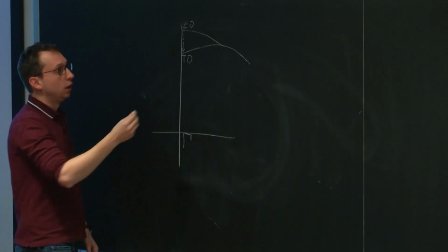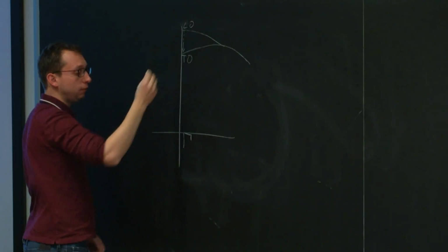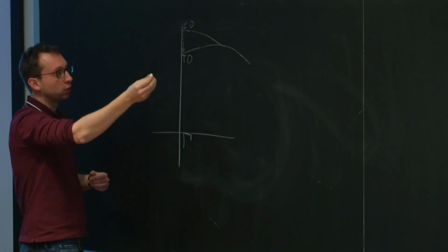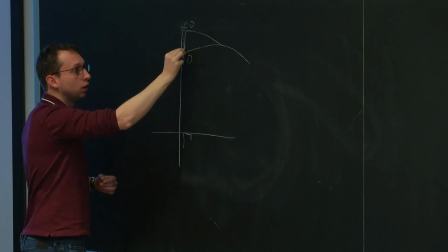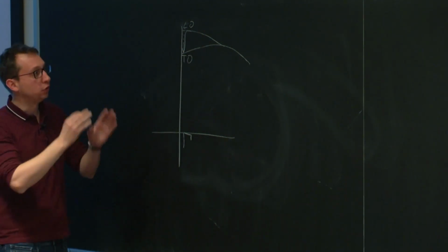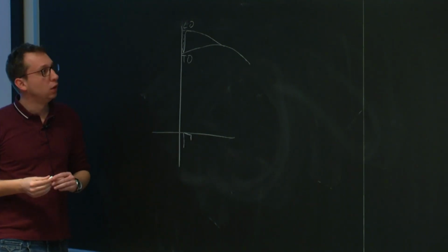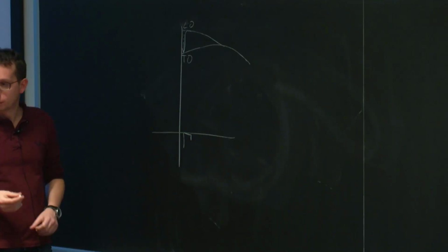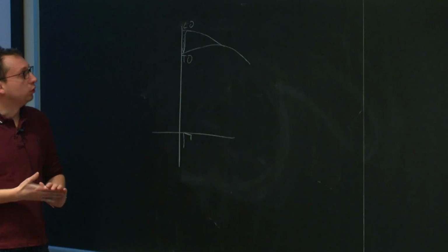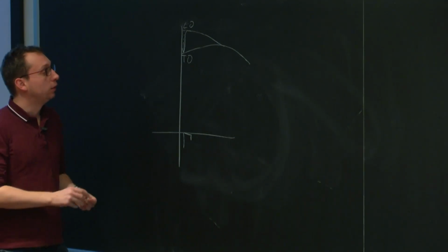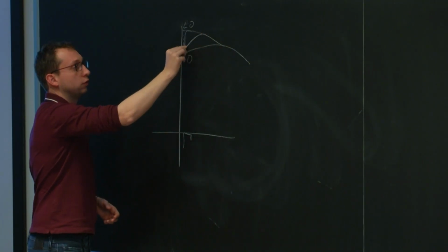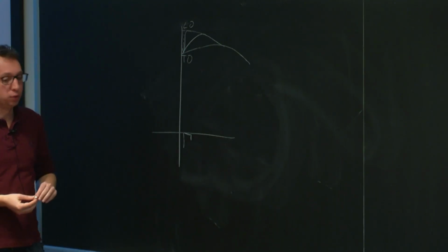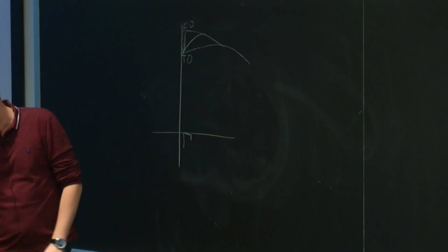There is no more splitting. With a little bit of doping, what happens is that you have the LO splitting at shorter wavelength, but then when you get to the very long wavelength, it's screened and it goes back to that, which is something almost impossible to see with phonons. If you are in this case, you have to interpret it a bit using physical intuition, and you can expect this LO going back to the TO in some place inside the Brillouin zone. You don't know exactly where.